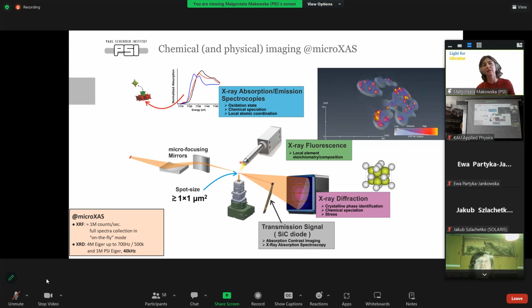We always had a manipulator. That would be the case for some ex situ experiments, where we have a manipulator for the sample, which can move the sample in all directions, X, Y, Z, also with a rotation and with a swivel. So we could also correct for the alignment. Simultaneously, we were able to measure fluorescence and diffraction from the sample during the scanning over the sample, and also the transmission signal through the sample. So these three signals we could measure at the same time using a monochromatic beam.